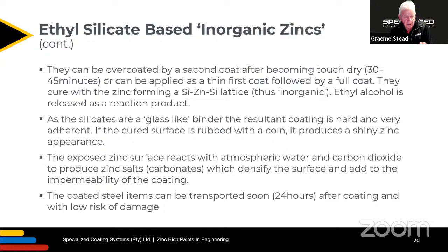The exposed zinc surface reacts with atmospheric water and carbon dioxide to produce zinc salts, carbonates, and all the other salts that Simon was talking about, which densify the surface and add to the impermeability of the coating. And the coated steel items can be transported soon, 24 hours after coating, and with low risk of damage.